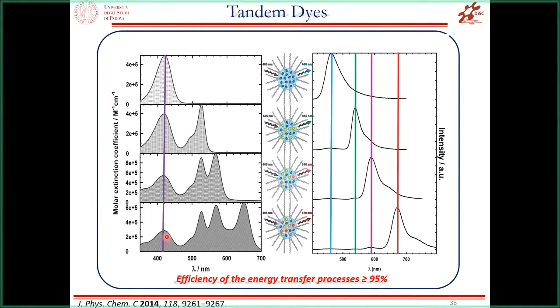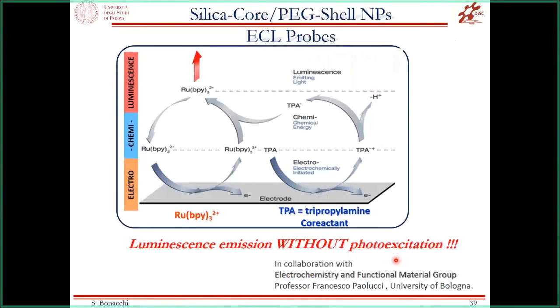And so we were able to obtain a very nice tandem dye with a very large Stokes shift, if you consider that here we can excite at 400 nanometers and obtain an emission, in the last case, at 700 nanometers with a very high efficiency in energy transfer processes. So just before concluding, we also use this kind of approach to enhance the performance of this silica nanoparticle.